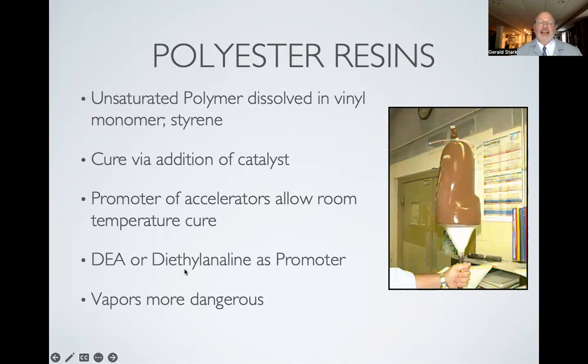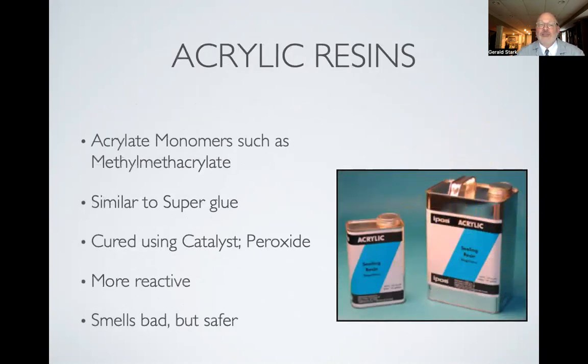I'm sorry, diethyl-aniline was the promoter. And if 10 cc's soaked through your skin, you'd have permanent liver damage. So this was very dangerous, and the vapors as it was curing, once it was cured, it was fine. But if you had mixed too much or too little of the hardener, sometimes people would say, I don't measure it, I just give it 2 good squeezes. If you didn't mix enough hardener in, then it would continue to cure over time and cause some chemical exposure issues. Acrylic resins were much more safe.